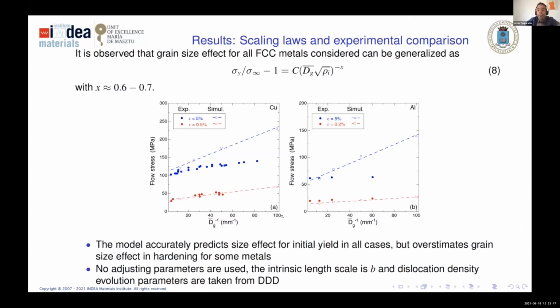Okay, so this is due to the way we incorporate the gradients through the GNDs in the Taylor model. Then we can say that this is something that we want to improve, but I want to emphasize, and that's why we're quite happy with this model, it's published in the JMPS in 2020, that the interesting thing is that with a quite simplistic model, we're able to reproduce experiments without fitting parameters for many FCC alloys with quite good accuracy, considering more or less the physics of the problem.